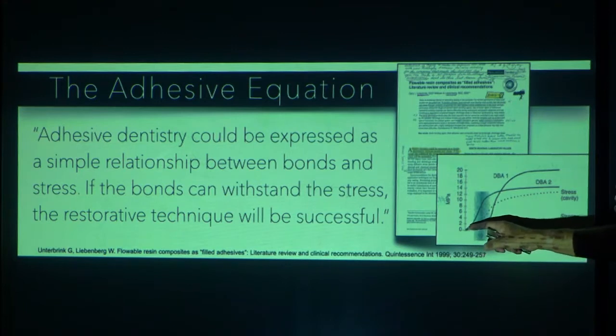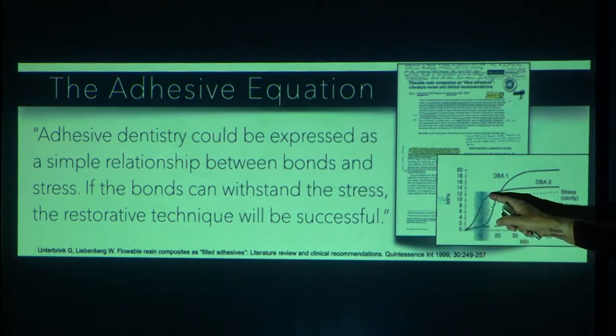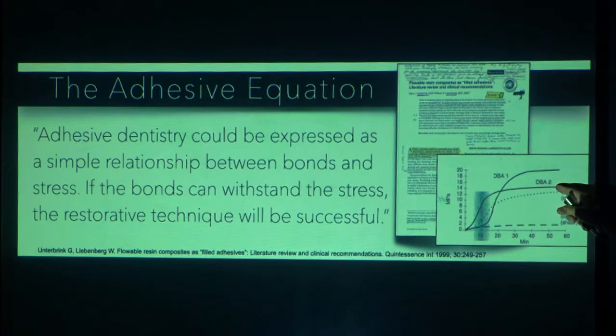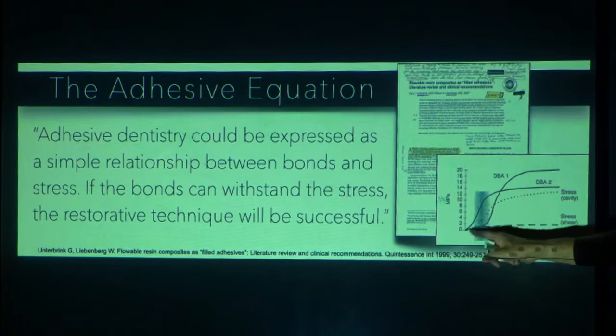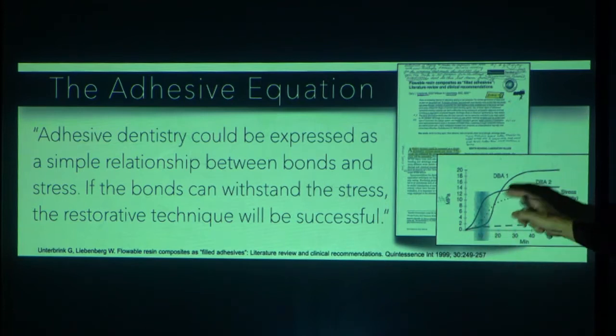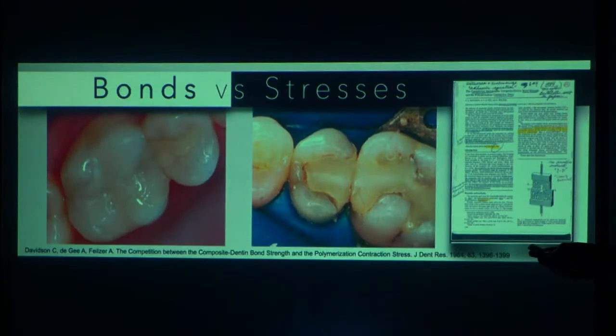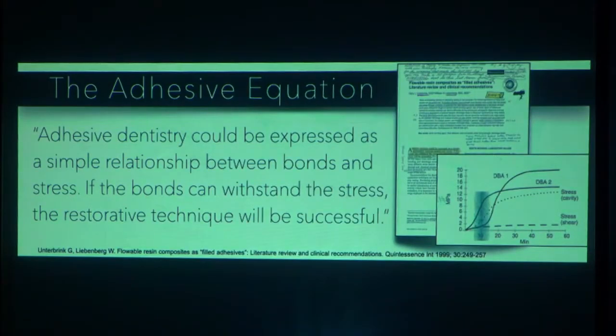Other bonding systems will have early polymerization conversion, but then a lower bond strength. But if you have the stress from the cavity, which we call the C factor, the stress from the cavity has to be compared on a time scale of when the polymerization strength is occurring. And so this stress from the cavity that we call C factor is very much a function of time. And so when I read these papers originally and read this first paragraph, I actually got this paper in a pre-publication form from Dr.